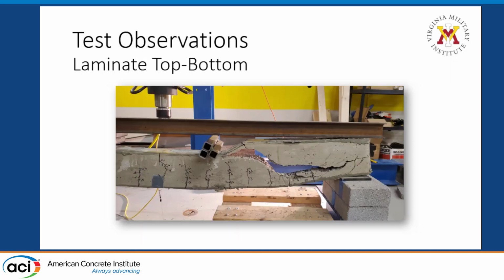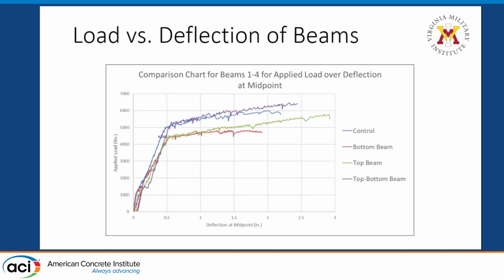And here's the double laminate, the coolest one. All right, and here is a graphical representation of the applied load over the deflection at the midpoint for the first 4 beams we tested. That's one of each type. You'll see the top bottom beam is above all the rest in terms of ultimate strength. And the control beam actually outperforms the single laminate beams, which is surprising, but we believe that's due to a lack of shear reinforcement.